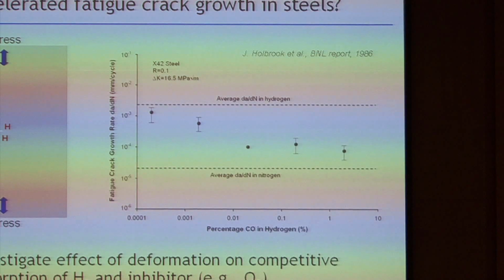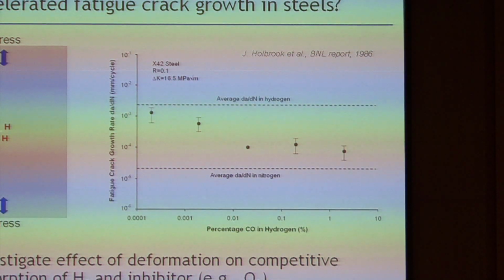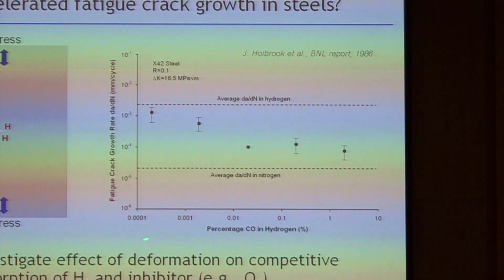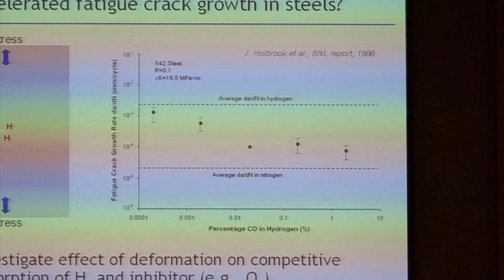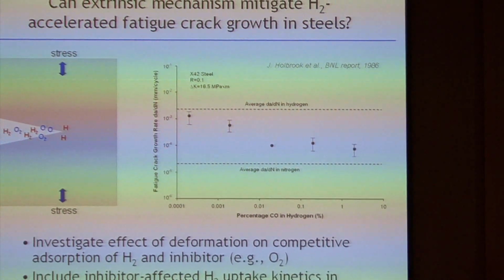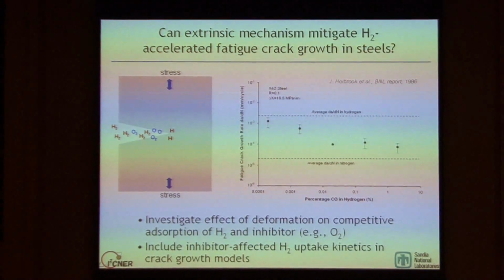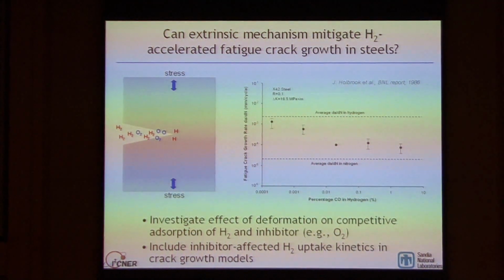The notion of what can happen with some of these gas inhibitors in hydrogen gas is that species like carbon monoxide or oxygen can dissociatively adsorb on the surfaces of these steels, which can prevent the adsorption and dissociation of hydrogen.